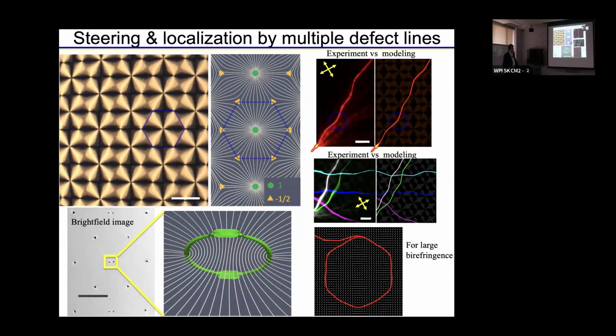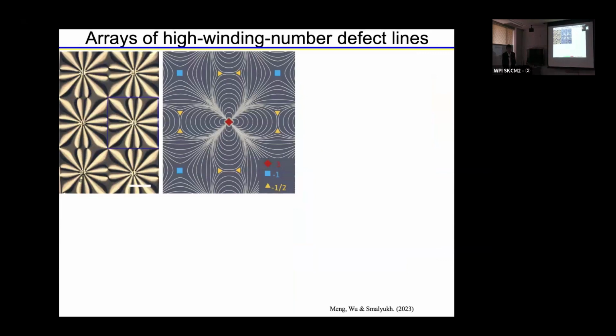Now, as we would have large birefringence, and large in this case would be on the order of 0.4, right? Then we would have light localized spatially. And then the challenge is a little bit that materials with large delta n at this moment are not room temperature materials. So in order to do this, you would have to heat the sample, because at room temperature there would be crystals with too many extra defects that scatter light, and that would also not host the optical solitons in their solitonic nature. But when we generate high winding number solitons, like the ones you see in here, then you will see we can actually spatially localize light with materials that are similar to the ones we use in our displays. So no new chemistry needed, just new types of lattices.